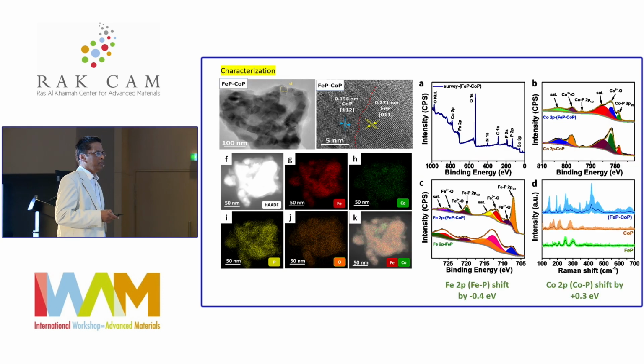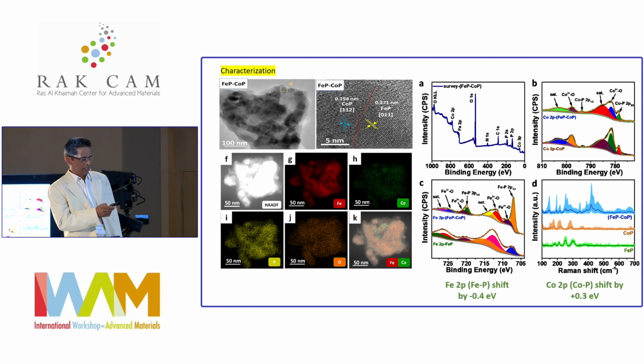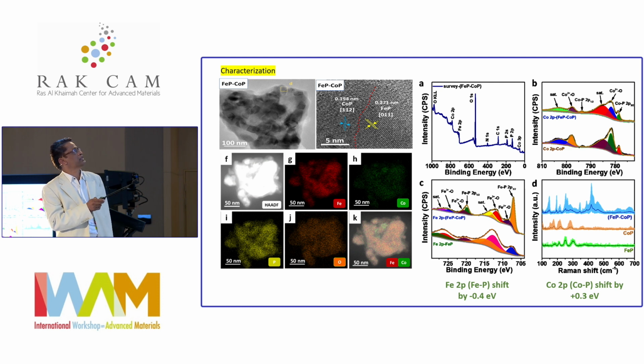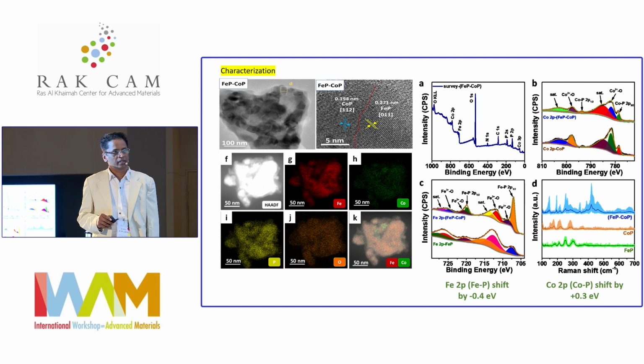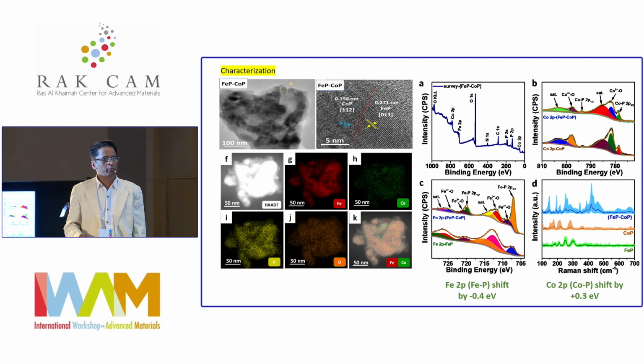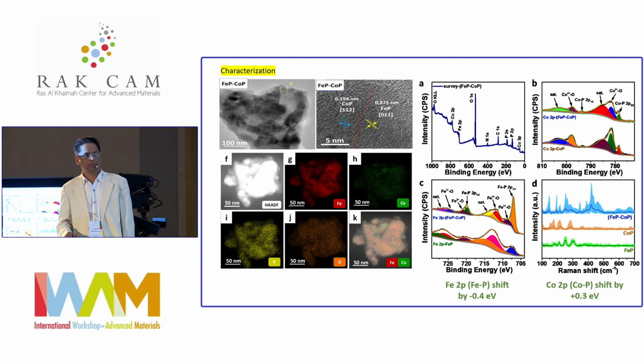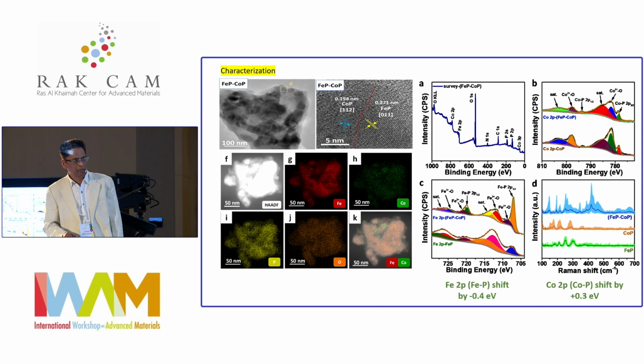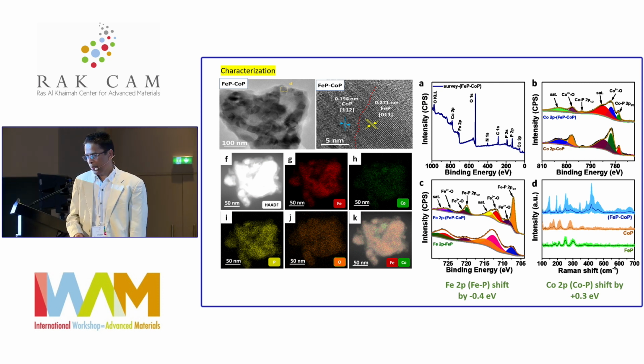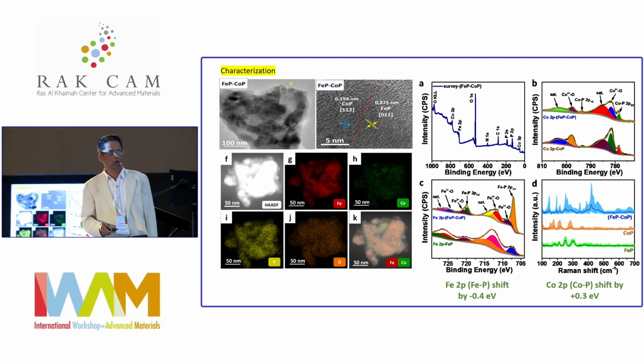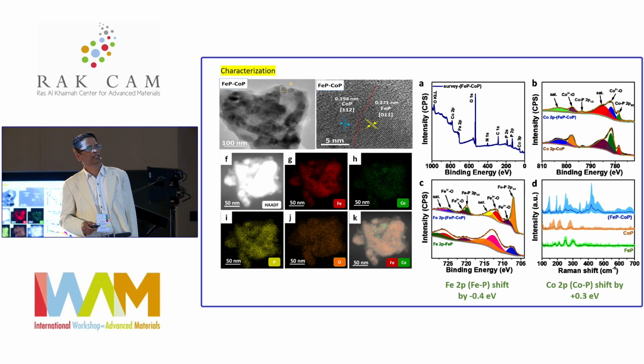All the characterization studies show the critical interfaces. You can see that the FeP-CoP mixture gives nanoparticles or heterostructures between the particles, as seen from the TEM, and EDAX elemental mapping shows the presence of iron and cobalt, one over the other. XPS analysis clearly shows the Co 2p peak shifts by almost 0.3 electron volt, whereas in iron you see a negative shift of 0.4 electron volts. This shows there is a charge transfer interaction path from cobalt to iron, which is interesting to look at.